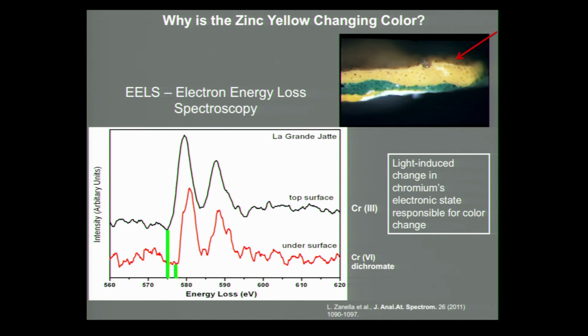And what this means is just what we had seen for the Van Gogh, that there's chromium 3+ on the top surface and chromium 6+, the dichromate that we should have, on the bottom surface. And so again, we're having a light-induced change in chromium's electronic state, and that's what's causing the alteration of the colors in this particular painting. And so again, once we understand the technology involved in the paint changing color, we can start to formulate a preservation strategy.